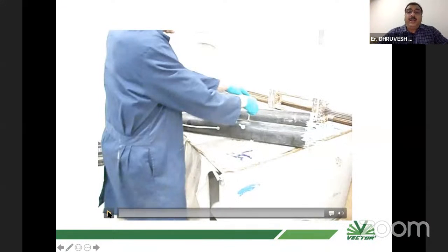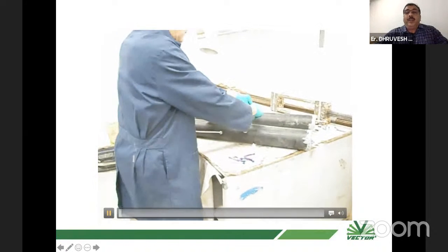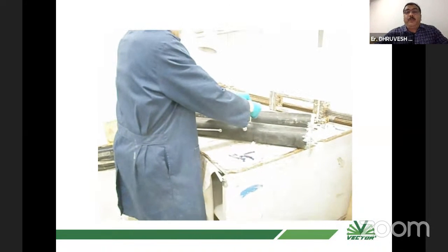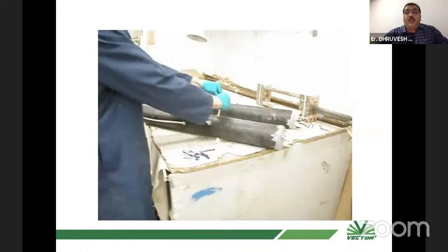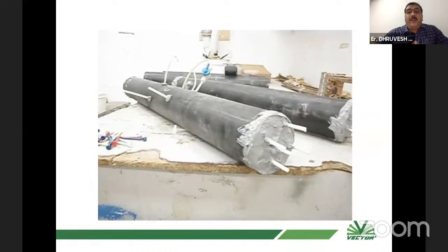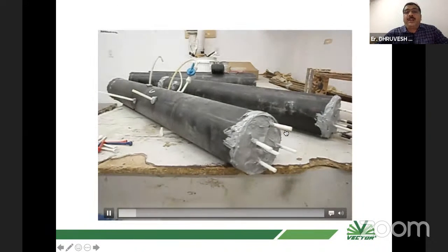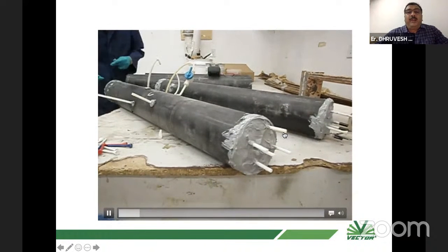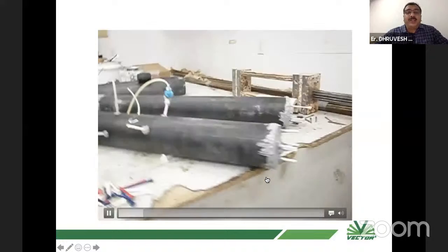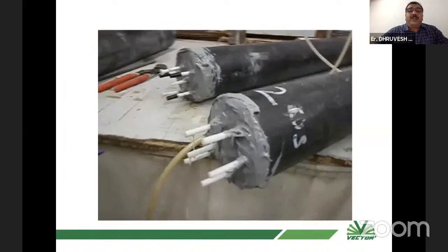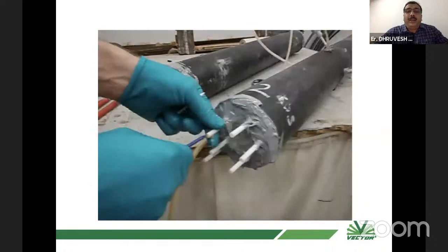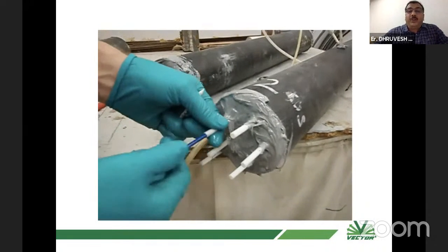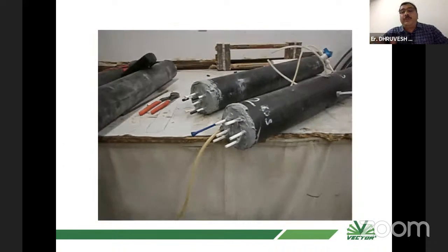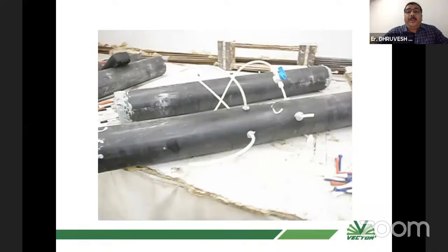And then we even tested, there's a small video, however it might not be too sophisticated, which shows how the grout comes if we pump from the center. We had put the port at the middle, and then we observed the grout flow. Obviously, as it is on top, the top one will have grout coming out. Then from the bottom, we started plugging it with a special plug. You can simply push it. It was designed as per the requirement, and we simply plugged one. It started coming from the different ports, from the different ends, and then we plugged almost all the